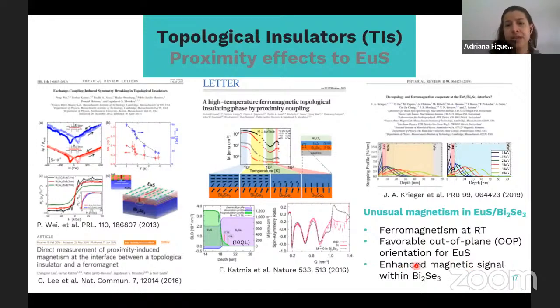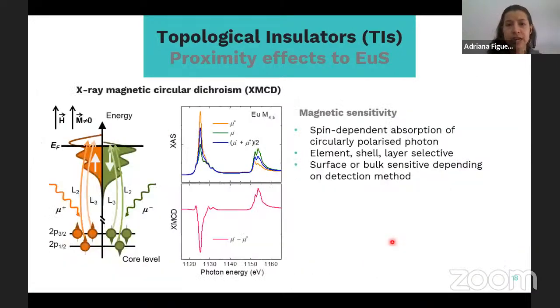And then the most remarkable observation is that there is an enhanced magnetic signal within the TI. So this is something that has been explored using a series of characterization techniques, but it is best to use one characterization technique that allows for this investigation at the local level, which is X-ray absorption spectroscopies, synchrotron radiation techniques. And this is what we have done. So we have used X-ray magnetic circular dichroism to explore in an element and layer selective way what happens microscopically at the interface of this europium sulfide with the TIs, right?